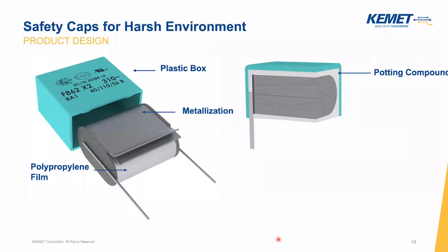There's a considerable amount of material science involved. Just to review briefly, a film capacitor is basically a wound element of metallized polymer film. For safety capacitors, that's almost always polypropylene. We do have some safety capacitors based on paper dielectric that are more specialized, but almost all our safety capacitors are based on polypropylene, because it has excellent electrical characteristics and self-healing capability. And then the metallization is usually some type of aluminum zinc metallization, which forms the electrodes of the capacitor.